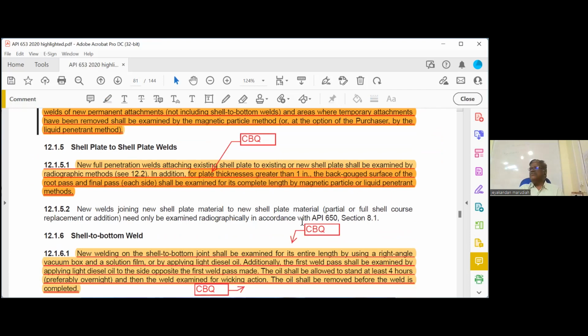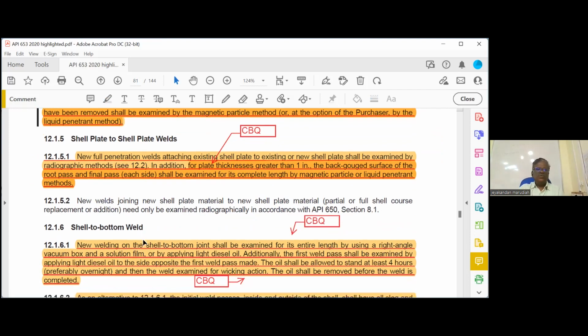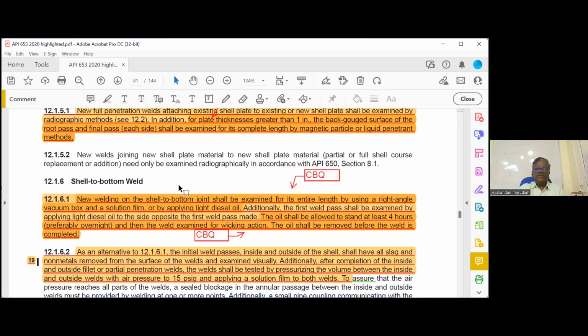Yeah. Now shell to bottom. Shell to bottom, if you are making any repairs, that area we have to do the vacuum box. Okay, that is important. New welding on the shell to bottom shall be examined for its entire length by using a right angle vacuum box or by applying light diesel oil. Additionally, the first pass shall be examined by applying the light diesel oil. The oil shall be allowed to stand for 4 hours and the weld joint examined for wicking. This oil shall be removed before the weld is completed. So how many hours you have to hold the oil? 4 hours. Okay.